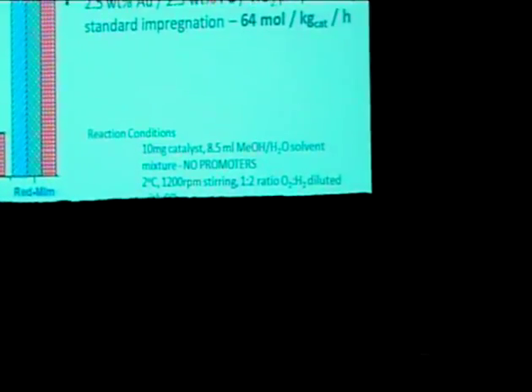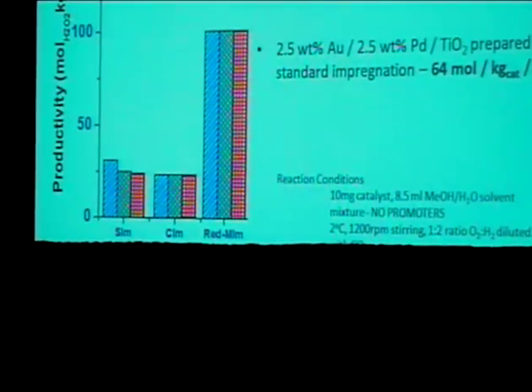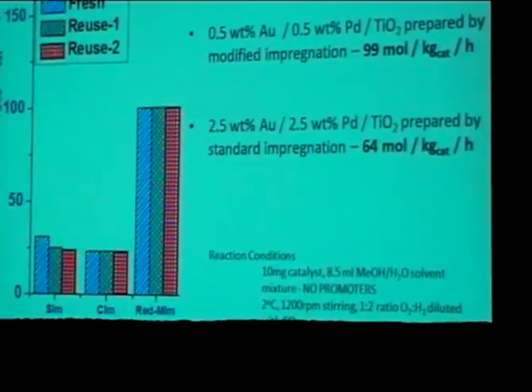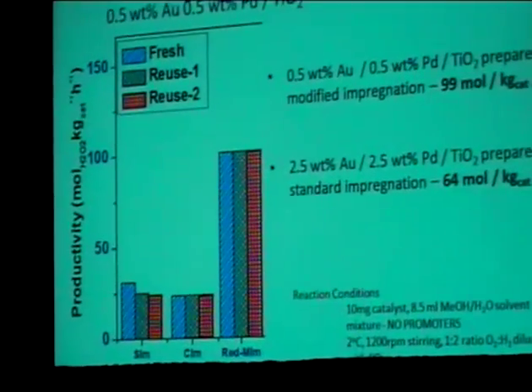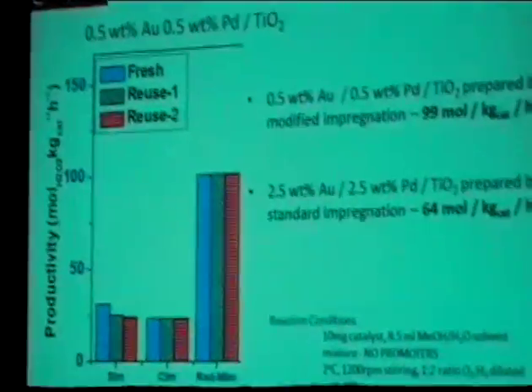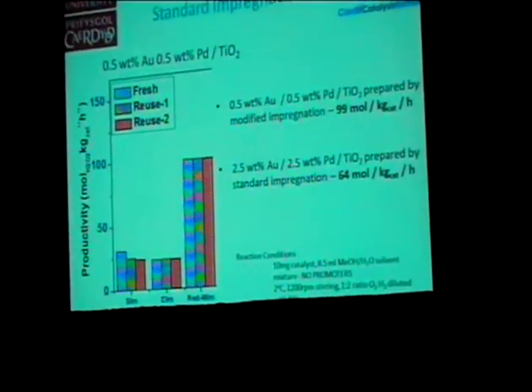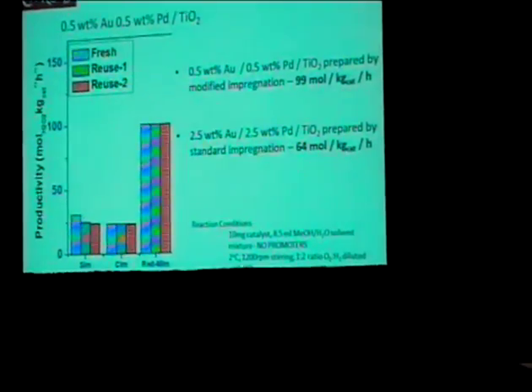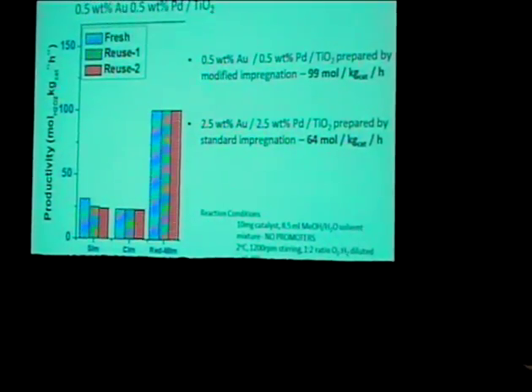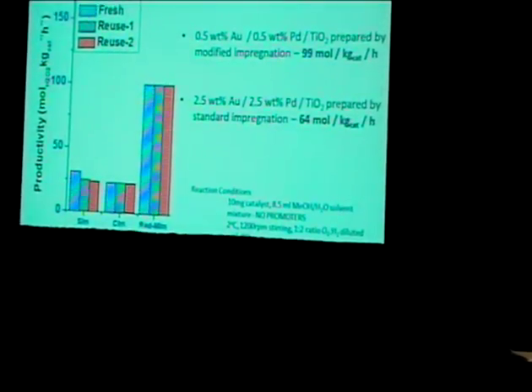So most of our work so far regarding these materials has been carried out in an autoclave in a batch system. And due to the long reaction time of 30 to 40 minutes, you do have to consider all of the subsequent reactions, the hydrogenation, the decomposition. So what you're seeing is basically the net amount of hydrogen peroxide left at the end.